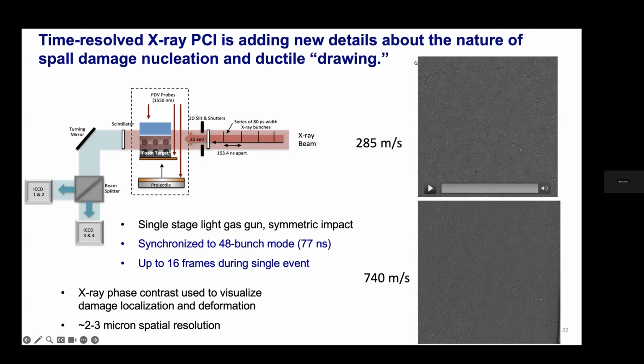So this field of view here, and as we're getting it ready for publication, we'll have all the scale bars on it, but essentially we have 1 to 2 micron spatial resolution, and the field of view ranges from 1.3 to 1.7 millimeters in that frame. So basically we're looking at a very detailed view in the middle of a much larger sample. So we design our shockwave experiment such that it's one-dimensional and we don't have any interference from release waves. But then we look at the center of the sample over just under 2 millimeters.